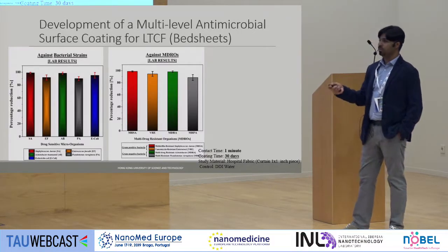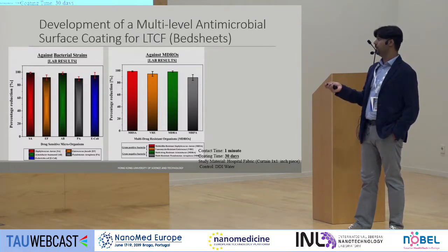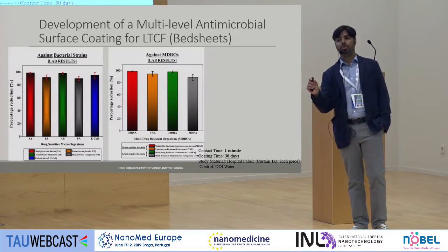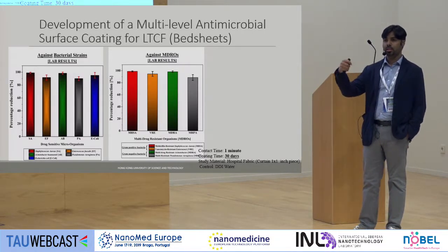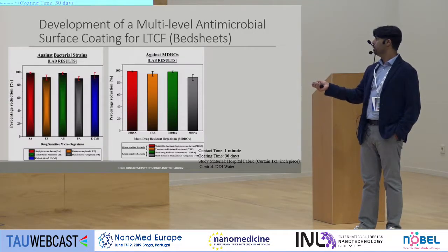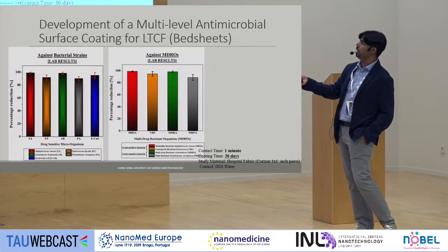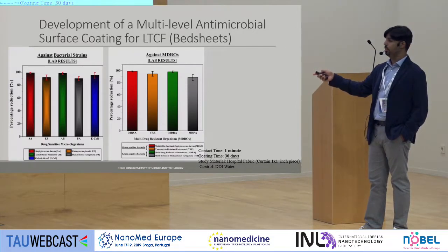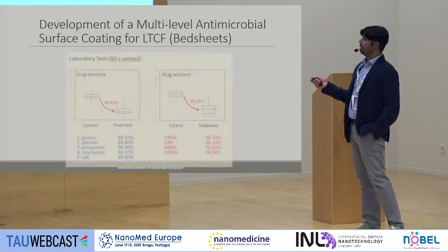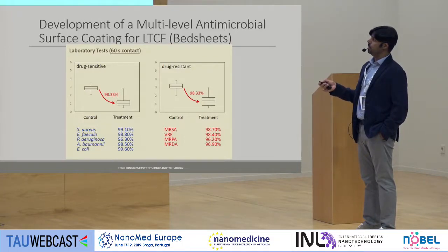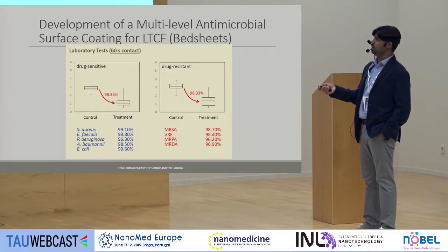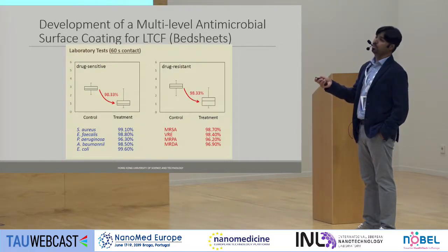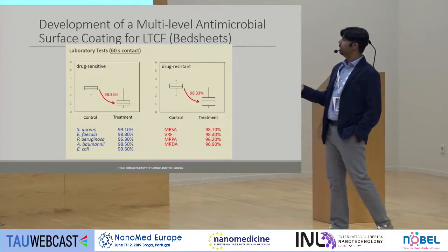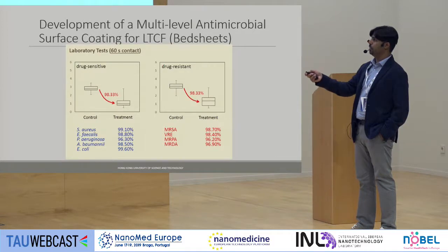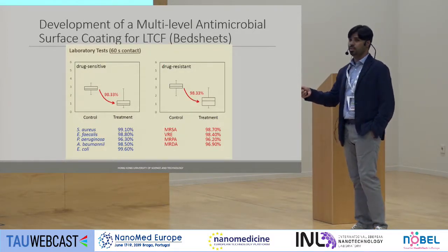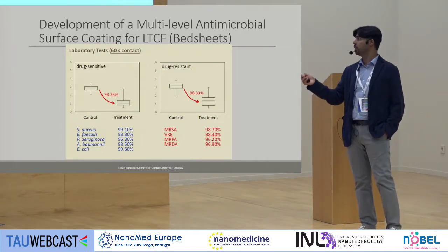And also the sustainability, keeping that in mind. So these results are for 30 days. For example, if I coat a piece with the coating, after 30 days of continuous exposure of bacteria to the surface, what will be the results? So we found around 90%, minimum 90% reduction in this control environment in the lab. So the summary of this one was for the drug resistant and drug sensitive ones individually. This is the reduction at day 30 with the 1 minute contact time. So we found more than 95% reduction for drug sensitive and drug resistant strains when the bacteria were exposed to this chemical coating.